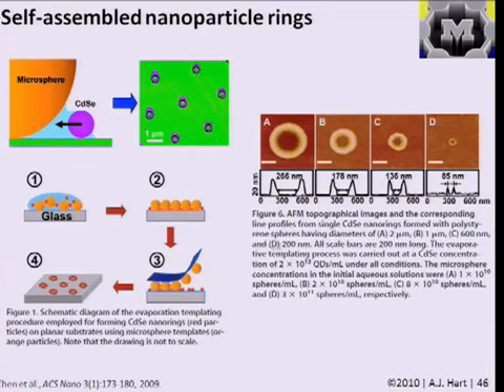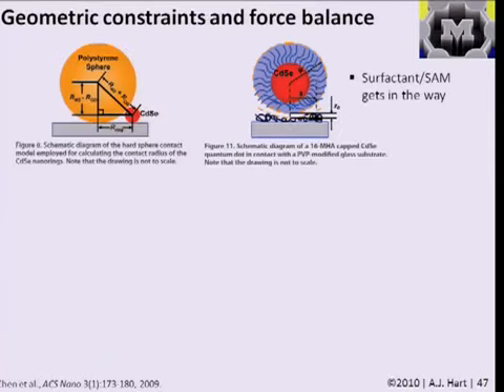So here, with a 200 nanometer sphere, there was a ring of about 85 nanometers, which is going to be determined by the de-wetting of this solution underneath the cover of this microparticle. And so they did the assembly process and then took a piece of tape actually and peeled away the polymer spheres, and we're left with these self-assembled rings. And what we'll get into next time is a more rigorous consideration to close this topic of the balances between forces in these considerations.